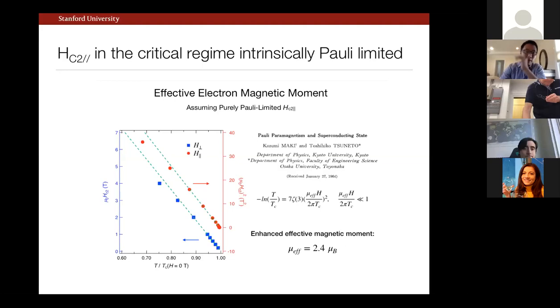Now, in the out-of-plane direction, as I had briefly showed you at the introductory part of this discussion, we see a nice kind of conventional upper critical field, so a linear variation. And so this indeed is conventionally associated with orbital depairing. And again, this gives you a coherence length of something like 3.5, 4 nanometers typically.